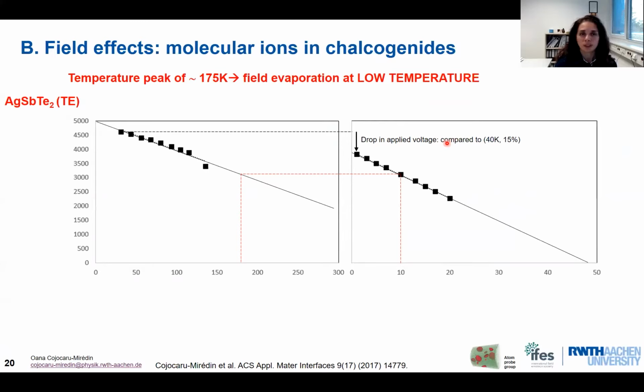Another important aspect is that, of course, the temperature plays a role, but it's not the main driving force for the formation of the molecular ions. For example, for the silver antimony telluride, where we have the highest fraction of molecular ions, about 60%, we measured a peak temperature of about 175 Kelvin. So this is a pretty low temperature on the tip. Of course, this peak temperature measurement might not be that reliable. We might have a big error while measuring this temperature, plus or minus 40 Kelvin, as was stated by some of the authors.